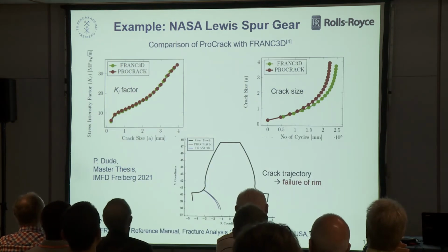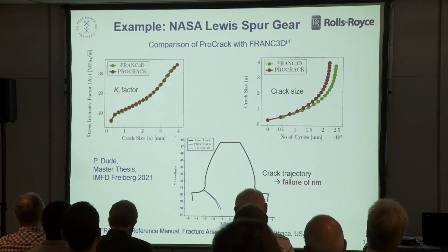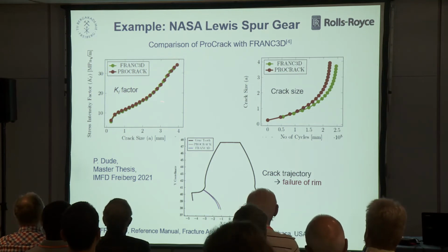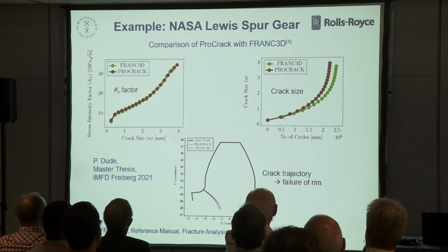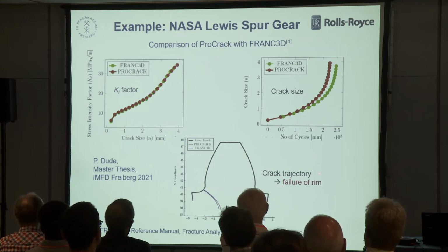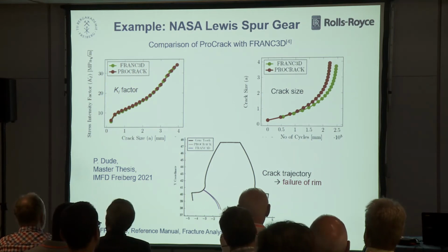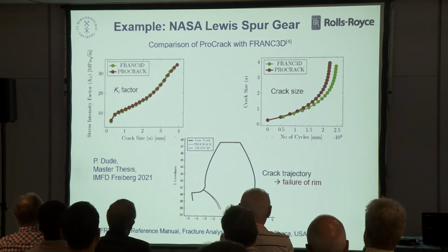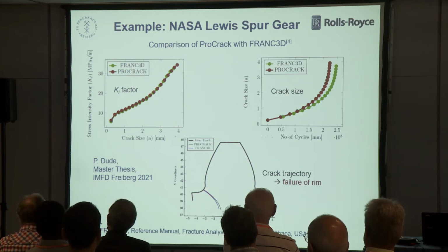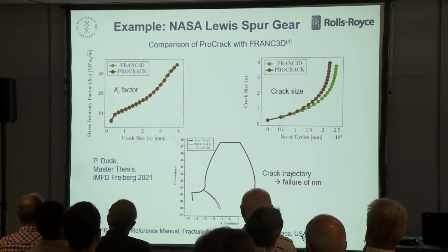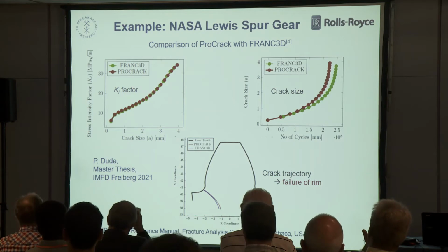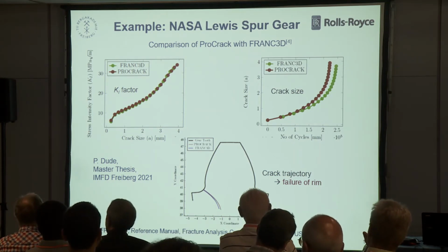And here is a comparison with Franc3D, the K-factors versus the crack size. So we find very good agreement, and consequently all the crack growth simulations, crack size versus number of cycles, fit very well. Moreover, the crack trajectories are the same in both simulations. But this results in a fracture of the rim, which is most detrimental. If the tooth would break, it would be better. So thanks to Mr. Dude.